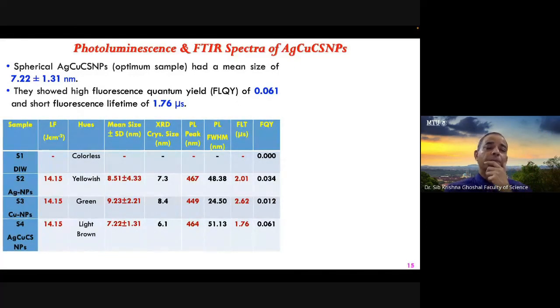As you can also see, the mean size of the optimum sample that we produce at the laser fluence of these nanoparticles is around 7 to 8 nanometers. So these nanoparticles are highly effective for various applications, and here is the optimum laser fluence for the production of nanoparticles, 14.15 joule per centimeter square.